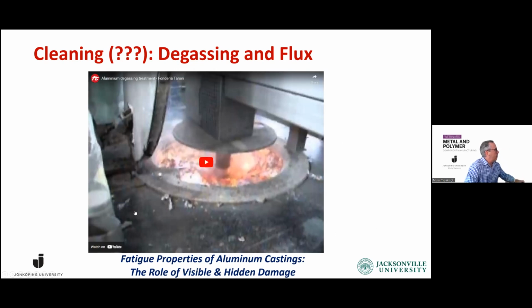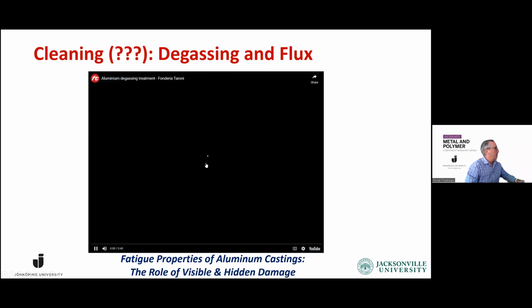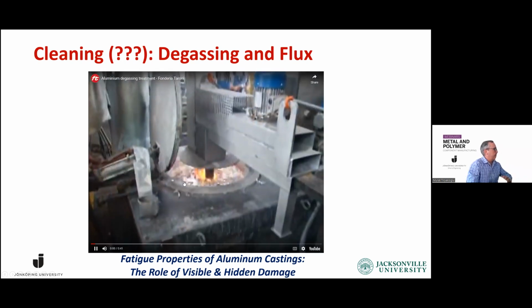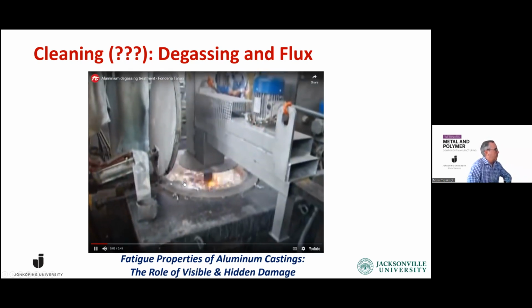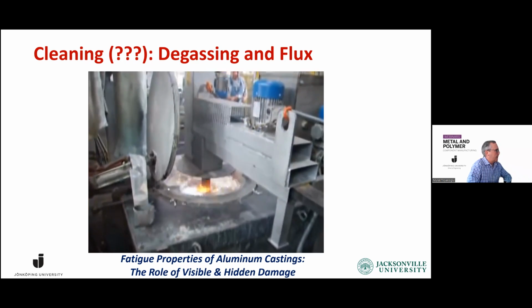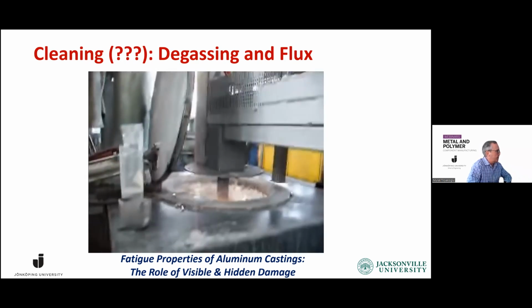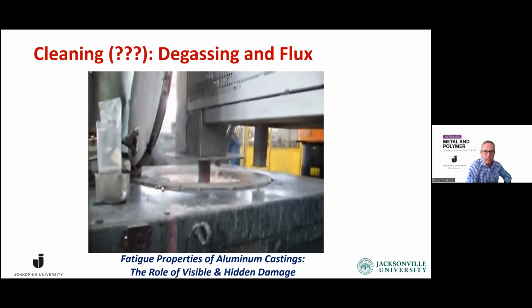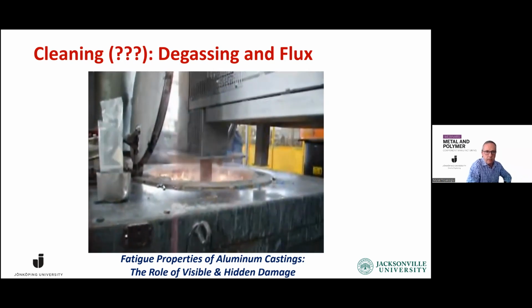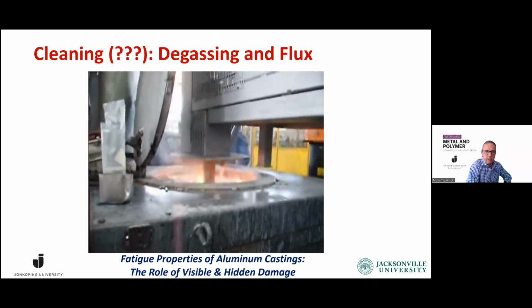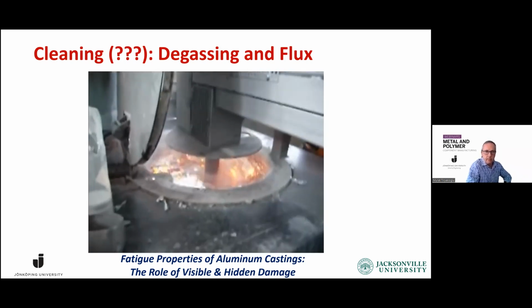Then one more thing that we do, cleaning. I put 3 question marks because I am quite confident that it does nothing as far as cleaning is concerned. We use argon and then use flux. It's a violent reaction. You see the vortex, so you see the surface being entrained into the body of the liquid metal.